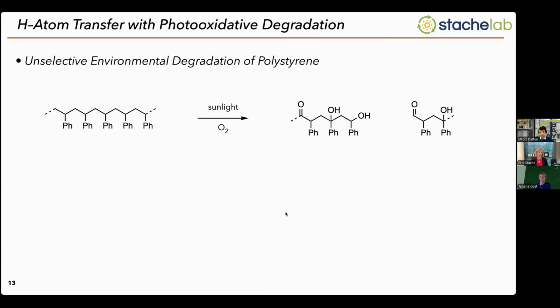And so we became very interested in the environmental degradation of polystyrene. So when this material gets out into the environment, it will break down, albeit very slowly and over hundreds of years. But the mechanism by which it breaks down is photooxidative degradation. So essentially sunlight and the oxygen in the environment will react with the polystyrene backbone. It'll start to oxidatively cleave. You'll get all this oxidized polystyrene, and it'll break down into smaller and smaller fragments. Now, of course, this process is not very selective, and it's also incredibly slow. And so we want to increase the speed and the selectivity for the degradation.